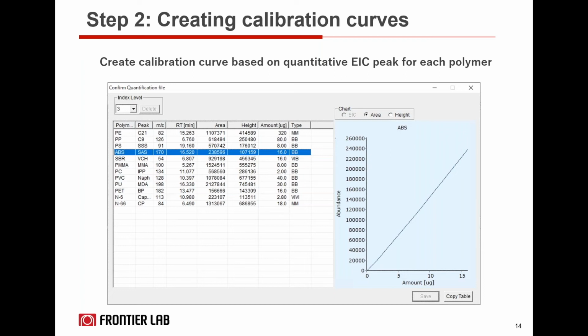The second step is creating calibration curves. In this case, your calibration curve is based on the quantitative EIC, the extracted ion chromatogram peak, for each of these polymers. The way FSMP 2.0 functions is that there is a characteristic peak, we call it the EIC, extracted ion chromatogram peak, for each of the polymers. And that's how F-Search will identify and quantify those polymers.